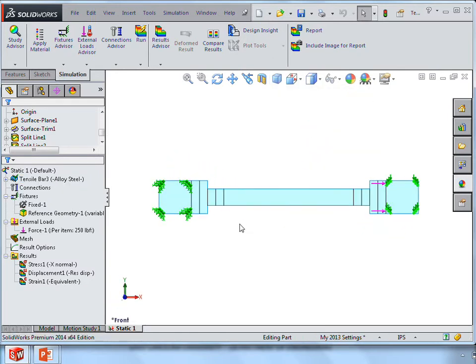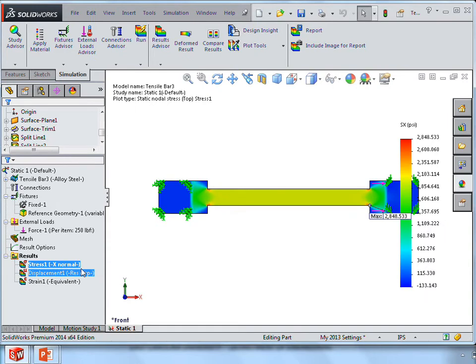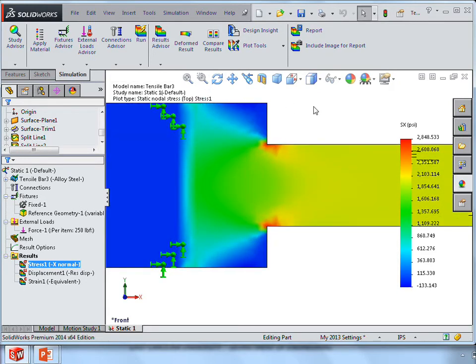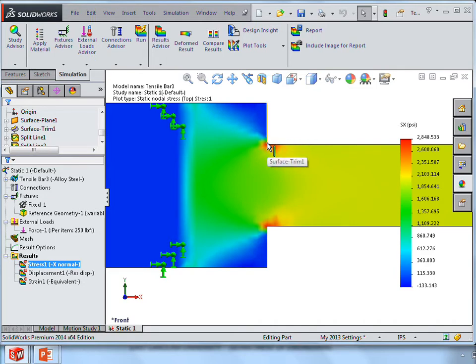Now, when I look at the stress, though, you'll see that the maximum stress is still greater than 2,000 psi, still quite a bit higher, 2,800 psi. And the high stress occurs right at this sharp corner. That sharp corner is called a stress concentration. So where we have an abrupt change in geometry, we're going to have a high value of stress. Now, in this case, if we tested this configuration, then we would expect that it would break right here. And our stress is not just our P over A of 2,000 psi, so we wouldn't get very good results out of this. We wouldn't get very repeatable results out of this test configuration.